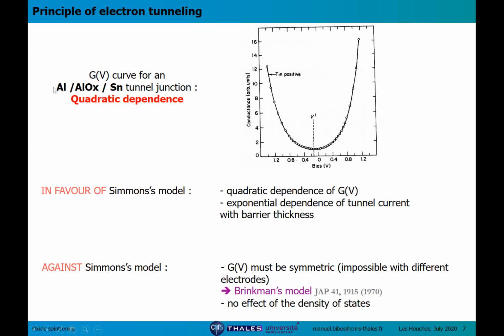So one electrode is aluminum metal, and the other electrode is tin, and the tunnel barrier is aluminum oxide. So you see from these conductance curves that we have a very nice parabolic shape, so very nice quadratic dependence of the conductance with the bias voltage. So this is what you expect from Simmons' model.